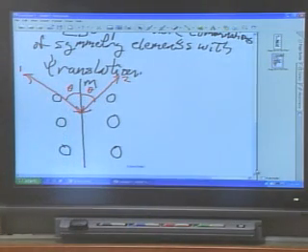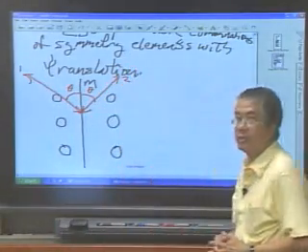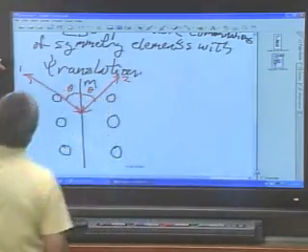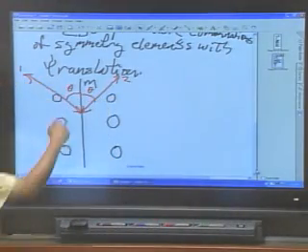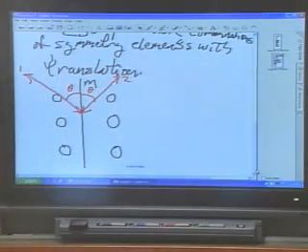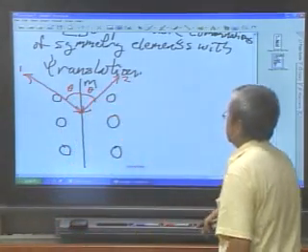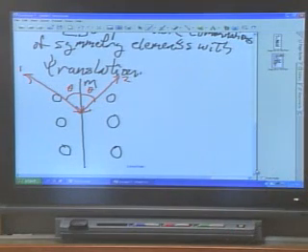And physically, the reason for that is the following. Suppose it's resistivity. You look at what happens when the electron is traveling in the crystal in this direction. Well, I would argue that because of the symmetry, whether the electron is going in the one direction or in the two direction, it'll see exactly the same thing. Because if it runs into the atom here and so forth, on the other side, since everything is mirrored across, when you come in that direction, it'll see exactly the same environment, and therefore the property should be exactly the same. So you prove that the property in the one direction and the two direction must be equivalent.